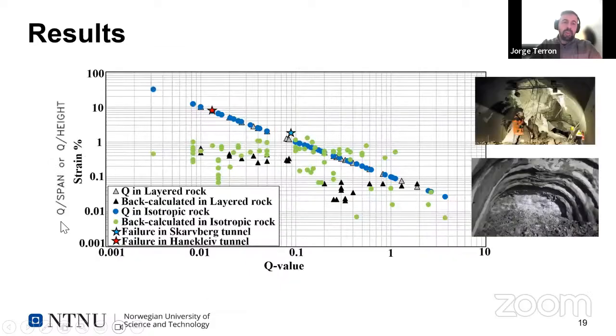So if we look at the tunnel strain or tunnel deformations calculated empirically with this formula of Barton et al. 1974, Q divided by the span, you get the blue dots and also the triangular gray dots plotted here, which is quite linear because the graph is plotted exponentially. But if we plot the actual calculations we did with the numerical analysis, the gray dots and the black triangles, you actually see a mismatch.